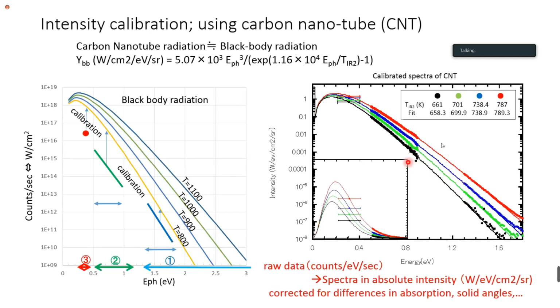Okay. So this is the data again, checked by fitting using this function, and you can get the temperature from here. The real temperature is this, and the obtained temperature is this, almost within a 1 or 2 degree difference. That's very nice. What I want to stress here is that you can have raw data, but with the spectrum calibrated in this way, you can get a spectrum in absolute intensity. So you know how many photons are coming from what you're observing. And this is a correction for almost all differences, like absorption and solid angle difference and so on.